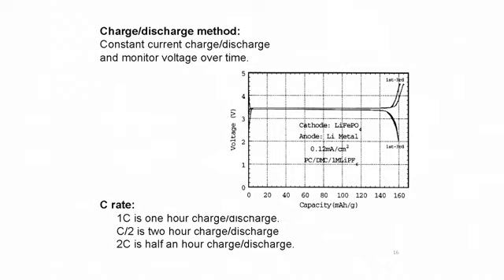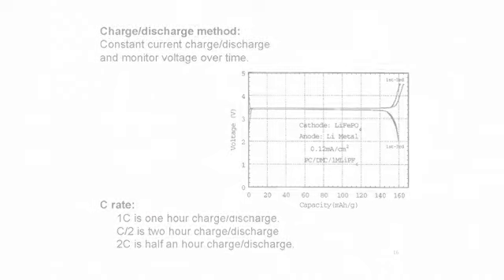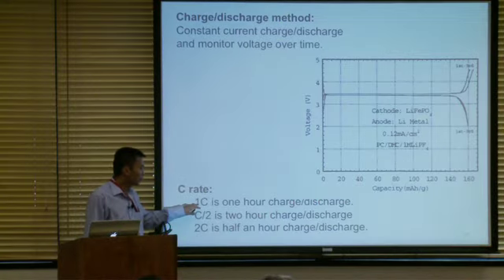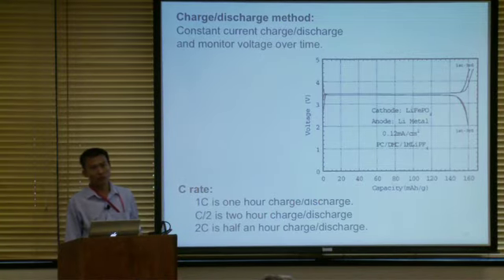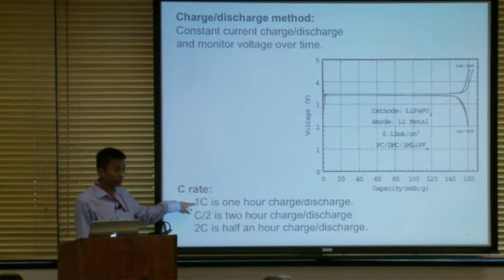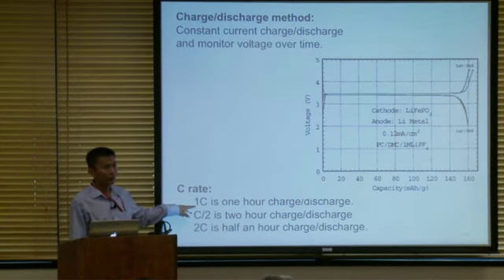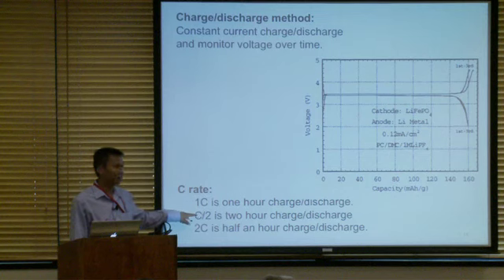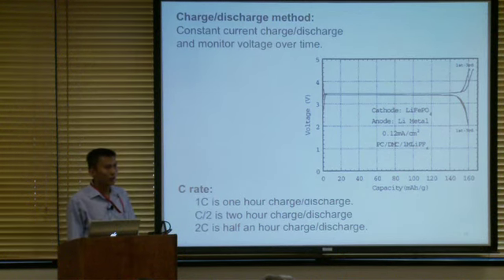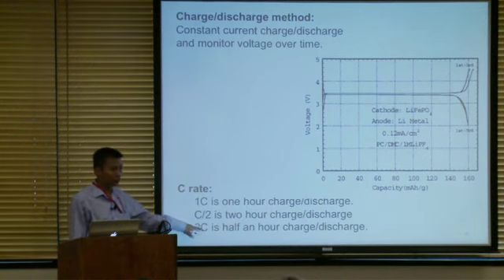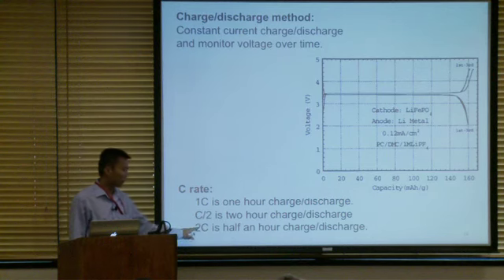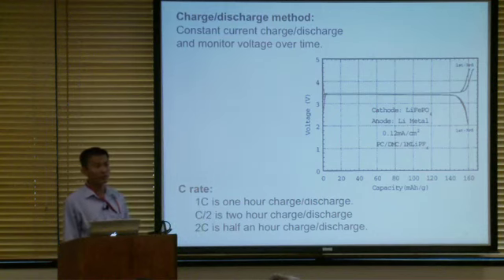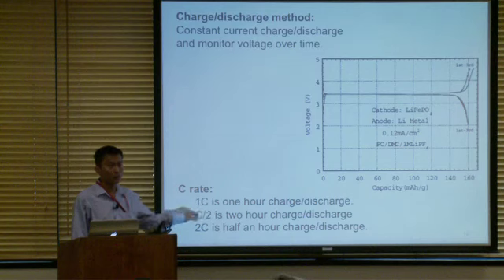People use this very often, C-rate. What does it mean, right? How fast you charge and discharge your batteries. If I use 1 hour to charge and discharge your battery, you call this 1C. If you use 2 hours to do it, it's C over 2. But if you use half an hour, it will be 2C. So put the 2 in front of C, that's faster speed, and put the 2 behind C, that's slower speed. That's just the convention. If it's a C over 3, that will be 3 hours.